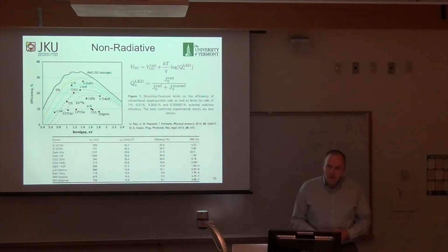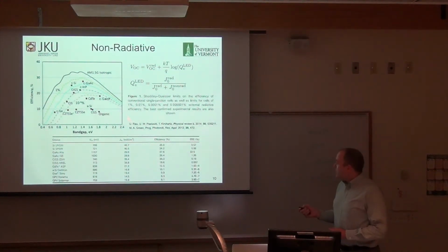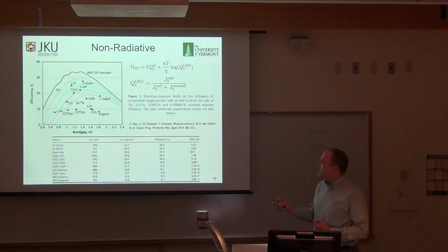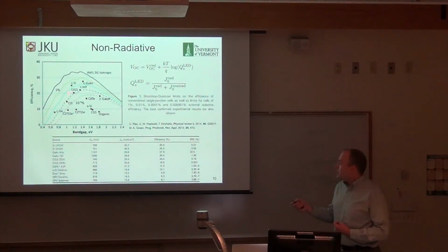But there's more. That paper assumes that every carrier recombination event results in the emission of a photon, right? But there are non-radiative recombination processes. So you can plot this same curve assuming that only a certain fraction of the recombination results in radiation. This green line here is 1%, 0.01%, 0.0001%, etc. down here. You see that it relatively quickly drops off.